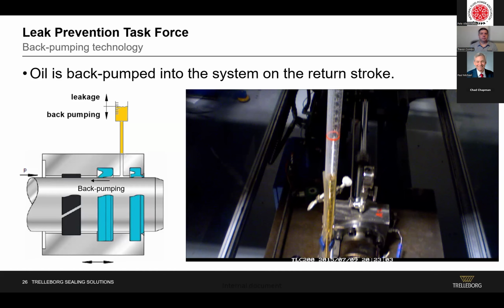Would a rougher surface be better for leaving a little bit of oil to remain on the rod? Yeah, that's a good point. So I think it might be important to look at the RMR that we talked about. I mean, there's a lot of factors that could be going into why that's happening. But the relative material ratio, if you don't have valleys that the lubrication can stay on the counter surface to lubricate the seal, then you could be seeing higher friction.